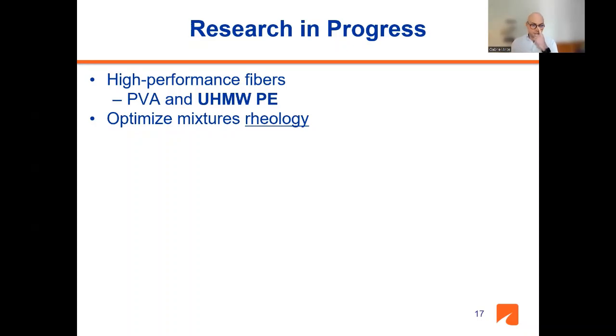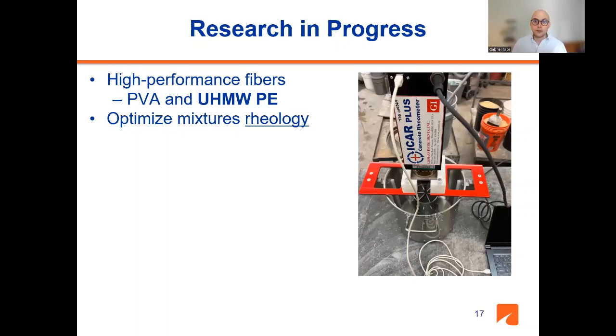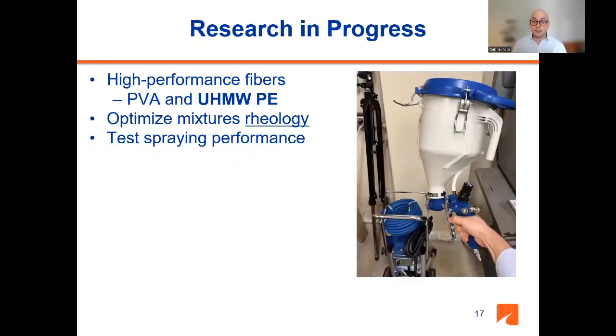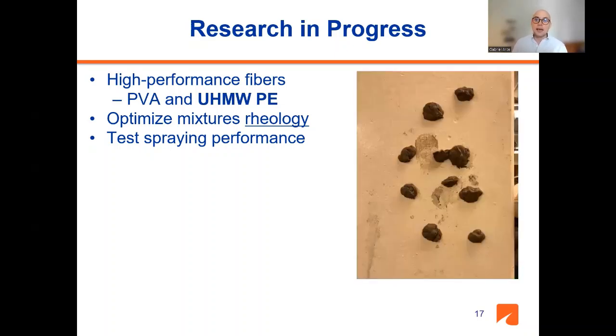Another thing that we're doing in this research is optimizing the mixture's rheology. So we're using a rheometer for this purpose to study scientifically the flow of this material, the plastic viscosity, yield stress, the thixotropy, which are important properties for this spray material. We're trying to test spray performance. We have a new spray system that hopefully is going to help us test how these materials spray in the lab.